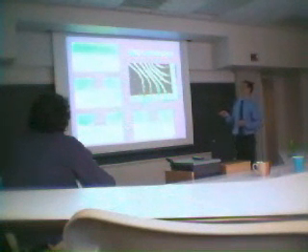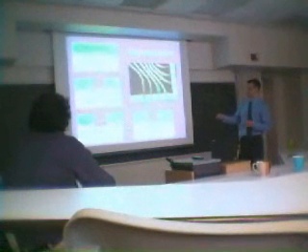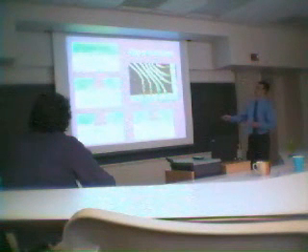off. And so to get around that, I spread a really thin layer of e-beam photoresist underneath, and then put the dry film photoresist on first, developed the dry film resist, dumped the trap in acetone, or squirted it with acetone for a really quick, short period of time to get rid of the e-beam photoresist that was under the exposed area, and then we put our metal down in these gaps. And that turned out to work in that we were able to make these really thin wires out here.